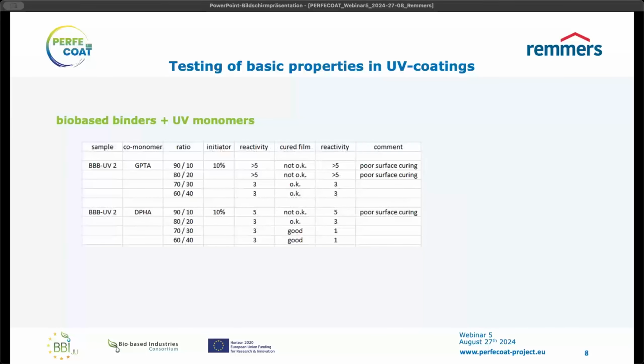Of course, we tested the same also for the binder number 2. As we have seen that there was a good deep curing from the beginning on and only some issues with the surface curing, we have skipped the difunctional monomer here and went directly for higher functionalities. And as you can see here in the bottom, especially with a hexafunctional DPHA, we could reach quite a good performance. We had a full curing already with 1 pass under the lamp, and it was resulting in a good surface of the cured film.